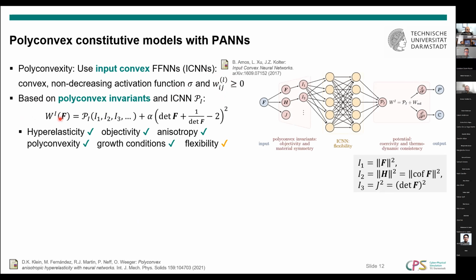So we can formulate a polyconvex neural network-based material model by, for instance, using invariants. You see the definition of the invariants over here, which ensure objectivity and which can also ensure the correct material anisotropy, material symmetry, and just inputting these invariants into an input convex neural network that gives us the strain energy and then taking the derivative. So in this way, we have a hyperelastic, objective, anisotropic, polyconvex model that is very flexible because we use a neural network inside, but we lose some flexibility because we use these invariants, which may not be sufficient to describe all of the possible material behaviors. And here we also enforce the growth conditions using this analytical term, which just gives us this desired behavior for the determinant of F going to infinity and going to 0.